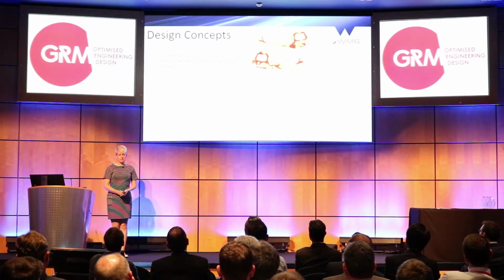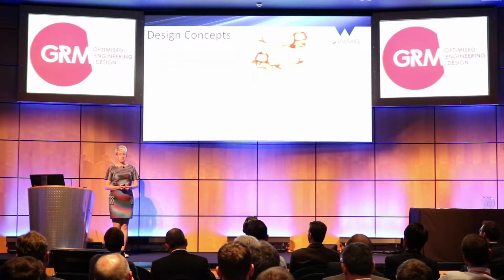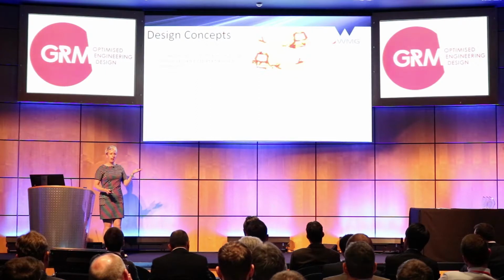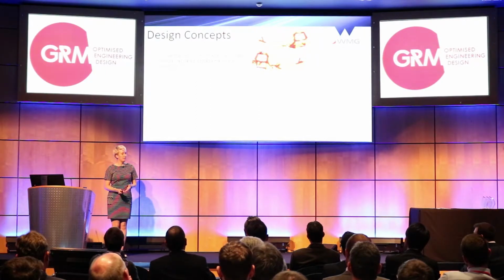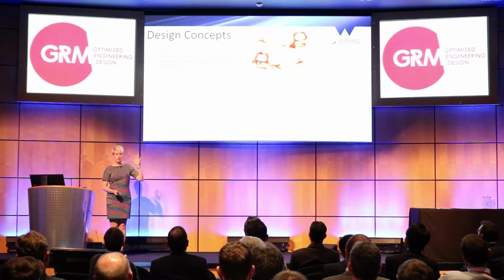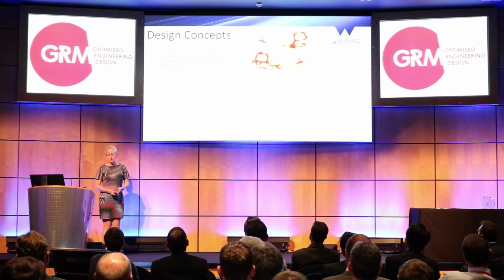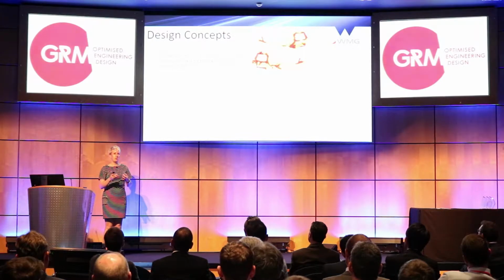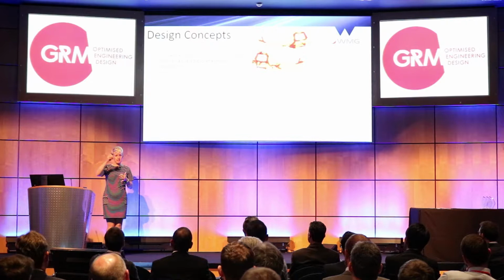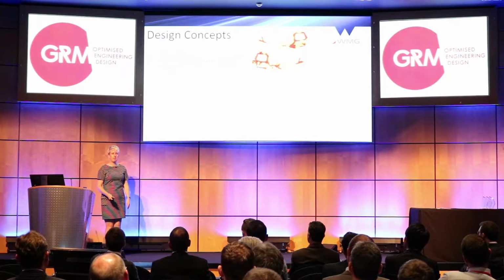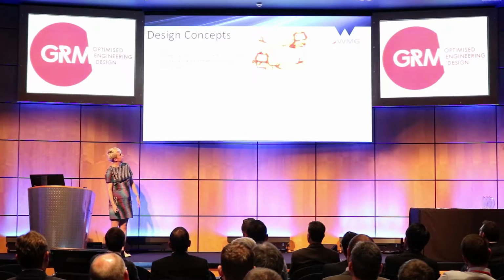So this was our first go at pre-preg and SMC, and this is where GRM really helped with their optimization techniques about where we need to put this SMC. So the SMC is red and the pre-preg is green. To meet the hard points of the package design, such as the anti-roll bar and the brake caliper, we had to create some clevises to attach to the rest of the vehicle, and that's generally where you can see these red areas.